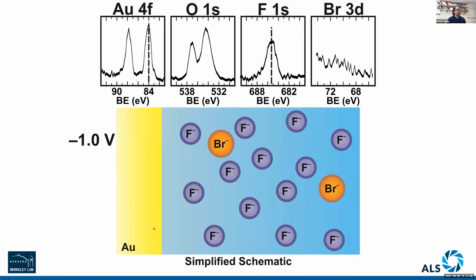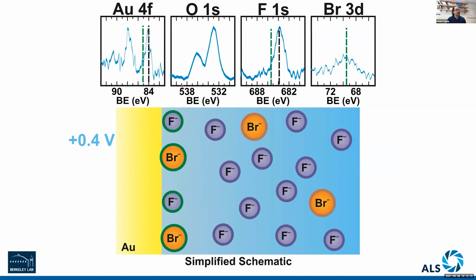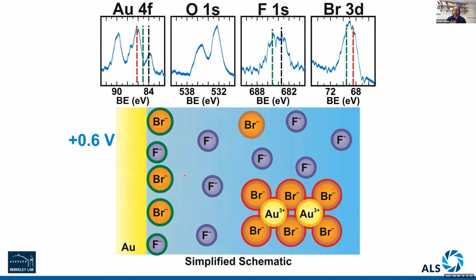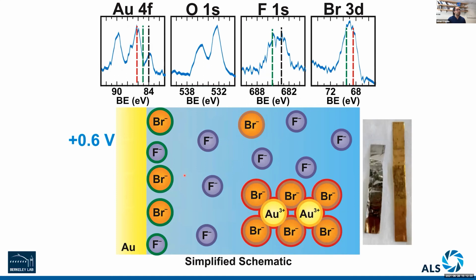So what is happening? If we visualize this, we have a very benign system in the beginning at -1 volt. Once we get to 0.4 volts, and I magnify the bromide 3D, we can see there's actually something starting to happen. We're forcing a specific adsorption between these ions and the gold. And then once we get to the 0.6 with the bromide, we're actually driving dissolution, electrochemical dissolution of the gold bromide into solution. And we can even see how it plates on our counter electrode. So now you can see an interfacial reaction driving the species in a very active way. So we can see interfaces evolve in these dynamic processes.